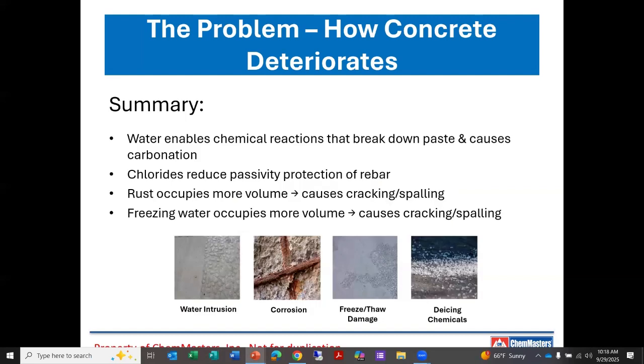So as a summary, water enables chemical reactions that break down paste and cause carbonation. Chlorides reduce passivity, the protection of the rebar due to the high pH in freshly poured concrete. Rust occupies more space, more volume, and that causes cracking and spalling due to its expansion within the slab. Freezing water also occupies more volume, more space, and that causes cracking and spalling within the concrete and oftentimes right at the surface.